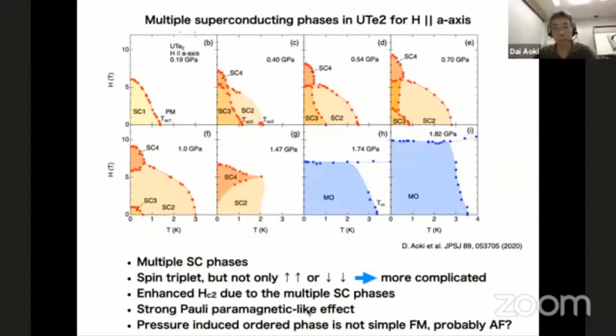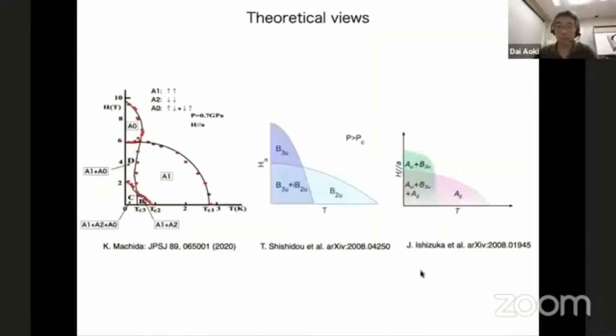So we can say that this multiple superconducting phase indicates a spin-triplet state, but it's not very simple. It may be more complicated than just equal spin pairing. And the strong Pauli-like behavior is also observed. This is also an interesting point, but we don't know what it is. This multiple superconducting phase is also discussed by theorists. Professor Machida, or Shishido and Ishizuka, propose this kind of phase diagram, but these are different from each other.